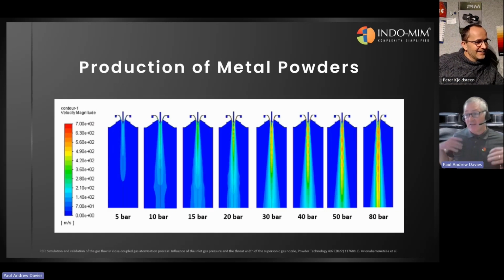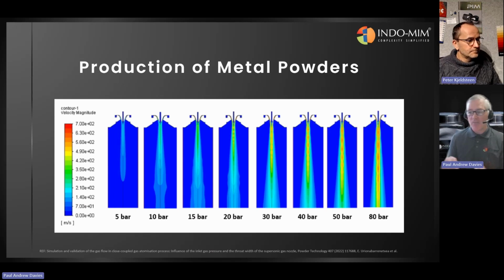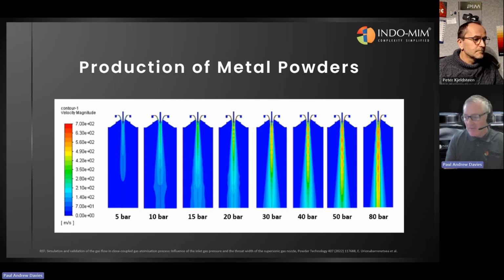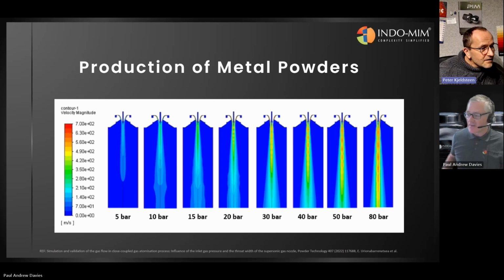And of course, adjusting the pressure of the gas can have an influence on recirculation. And here I've introduced a picture from research that's highlighting simulation of computational fluid dynamics. As I mentioned, the variables involved in gas atomizing are complicated. There is a synergy with rocketry in effect, because we're talking about high pressure gases, up to 80 bar here, and then you form shock waves because there are supersonic gases. Yeah, you can see the shock waves at the last three of them.